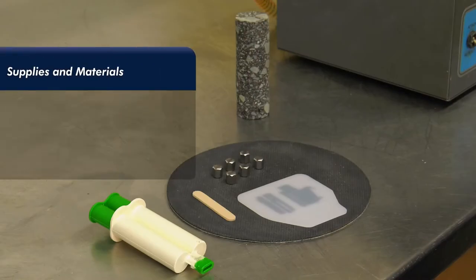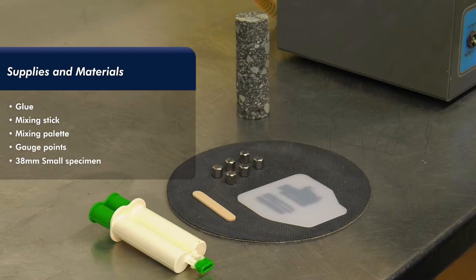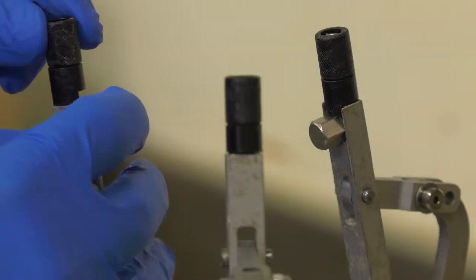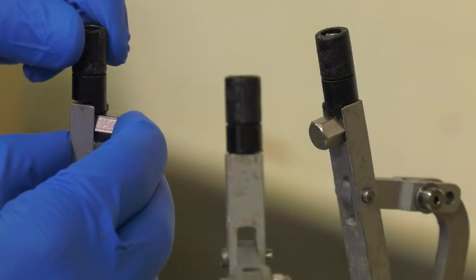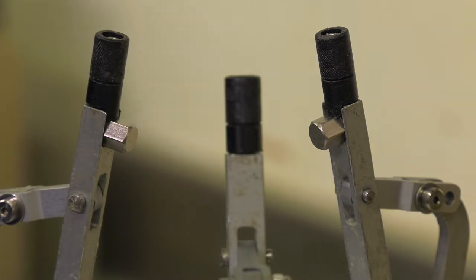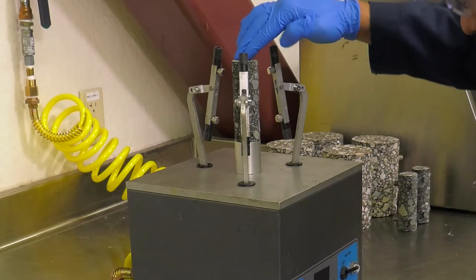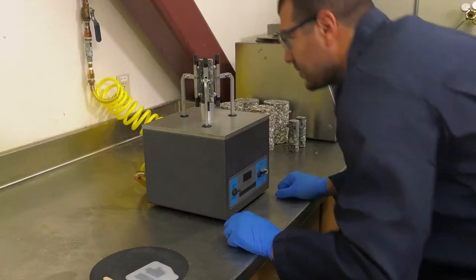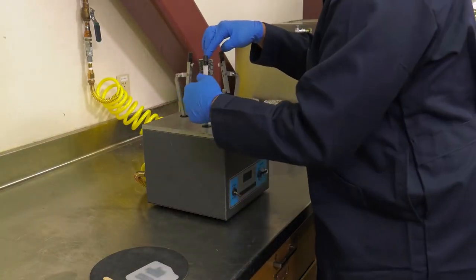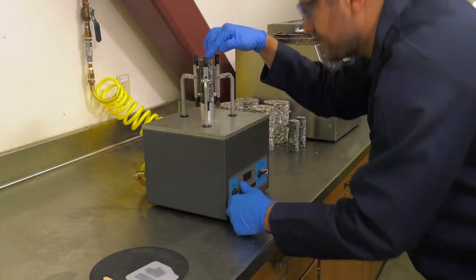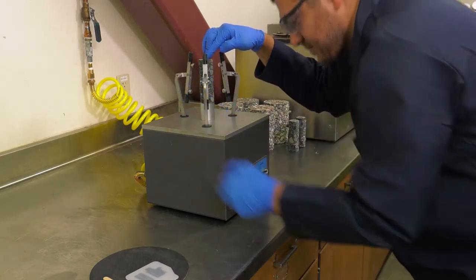Supplies and materials are shown here and include glue, mixing stick, mixing pallet, gauge points, and 38mm diameter by 110mm tall specimen. Start by installing gauge points on the setting arms for the fixing jig. Place the specimen on the stage to test alignment. Make certain the stage is horizontal and the gauge points will be attached in the middle of the test specimen. Adjust the bottom pedestal and/or setting arm if necessary.